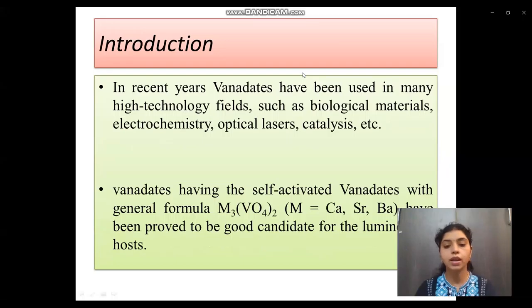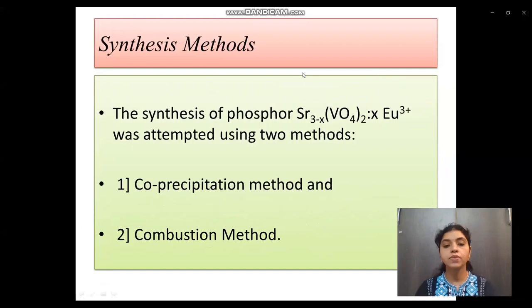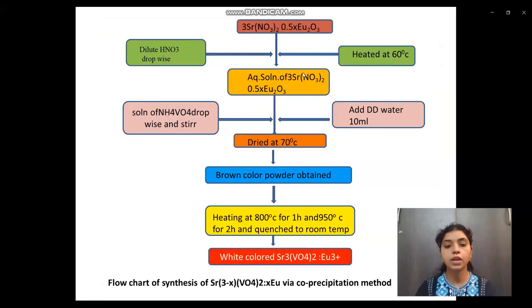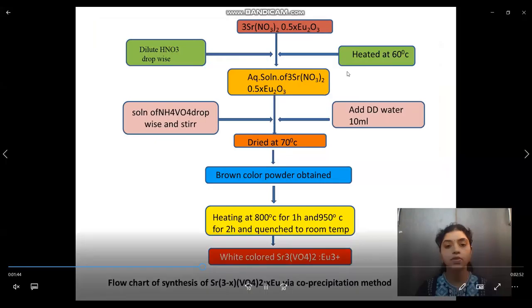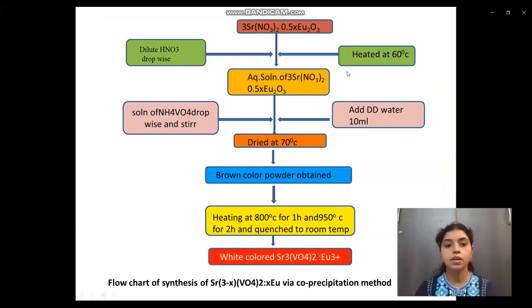This is a flowchart for the co-precipitation method. In this method, the precursors, strontium nitrate and rare earth metal oxide, were mixed together, and dilute nitric acid was added dropwise and the mixture was heated at 60 degrees centigrade on a hot plate. Then an aqueous solution of this mixture was obtained, and to this solution ammonium vanadate was added dropwise and stirred continuously, and some distilled water was added to this mixture.